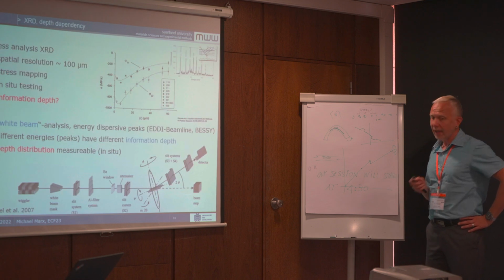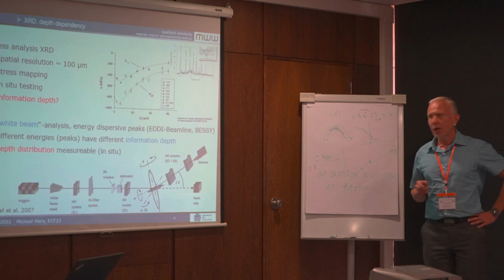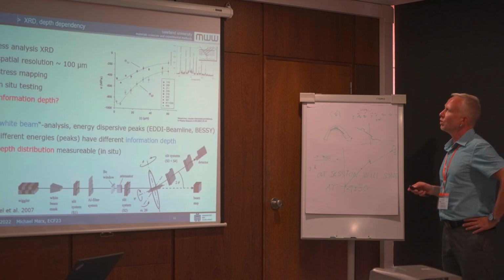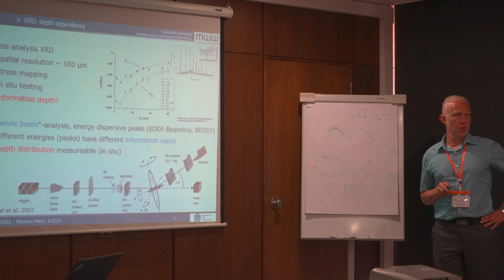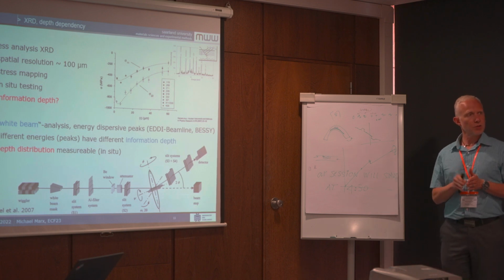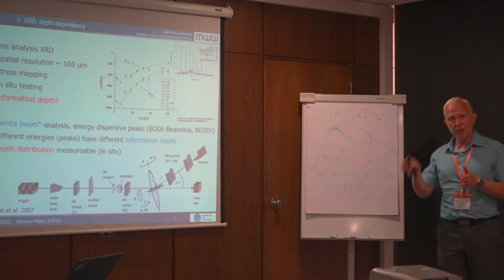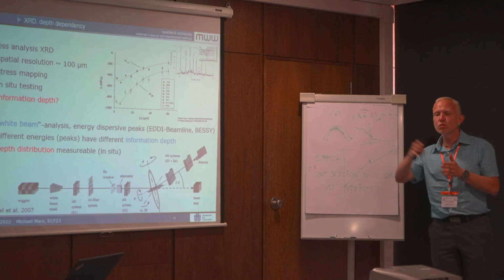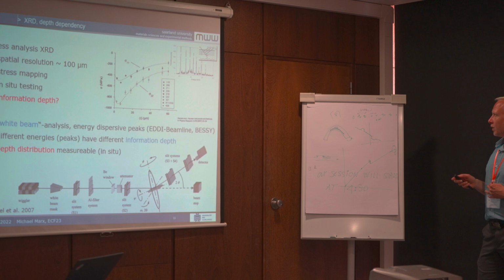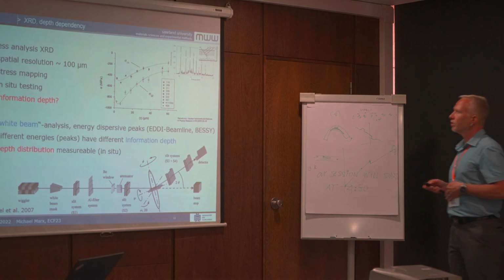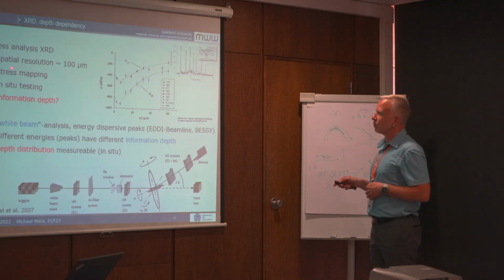Therefore, now we have our synchrotron data, and what can we do with this? First, we have a spatial resolution of 100 microns. So we measure step by step the 3D, or at the beginning the 2D shape of the plastic zone, or the 2D shape of the stress distribution in front of the crack tip, by a stress mapping.